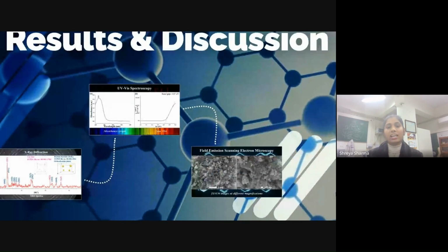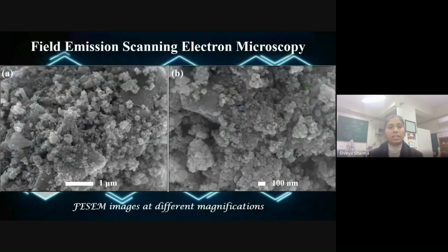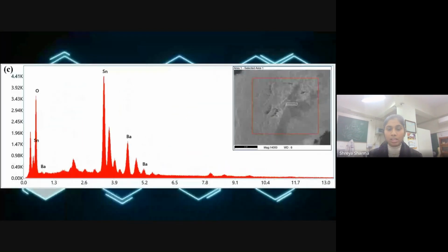The morphological analysis of the material was obtained by field emission scanning electron microscopy. Here we can see nano-sized polyhedral shaped particles, and as these nanoparticles have a high surface area to volume ratio, they are good for catalytic applications. Here we can see the EDX pattern obtained along with the SEM, and the presence of tin, barium, and oxygen was clearly shown here. The other peaks corresponded to carbon and gold coating, which was used to take the images of the material.